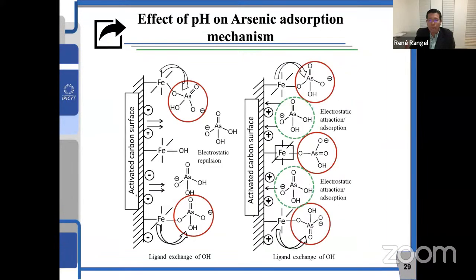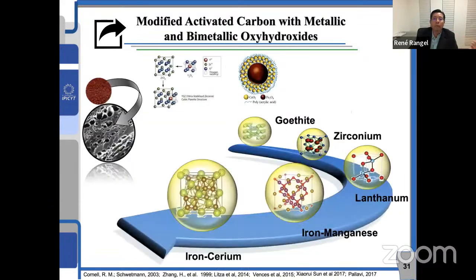In other words, I show you here in a schematic. If we have a material with a lot of metal oxide, but also with a negative charge, we will have repulsion of arsenic 5. But if we have a positive charge and also metal oxides, of course, the sorption capacity will increase. So here the message is we need to have a balance, okay? And this is very important. Well, that's what we learned from arsenic removal.